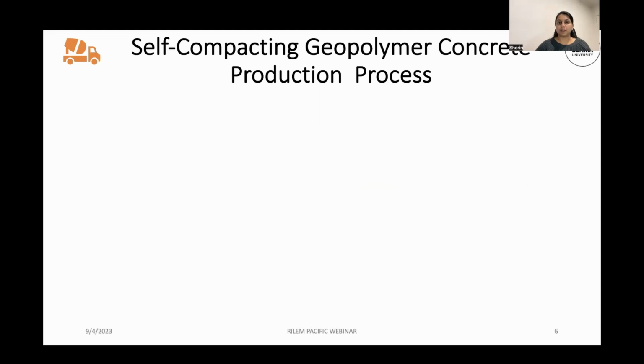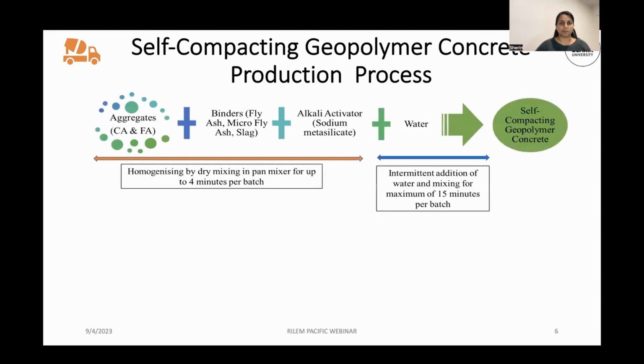In this slide, I'll explain the self-compacting geopolymer concrete production process. As the name suggests, this is a geopolymer concrete and hence it does not make use of any cement or cementitious products. The aggregates are similar to that of a conventional concrete. We make use of coarse aggregate and fine aggregate. The binder material used here replaces cement completely. Hence, we make use of fly ash, micro fly ash, and slag, which are waste products coming from industries, especially the thermal power plants or the copper production or the iron production industries.